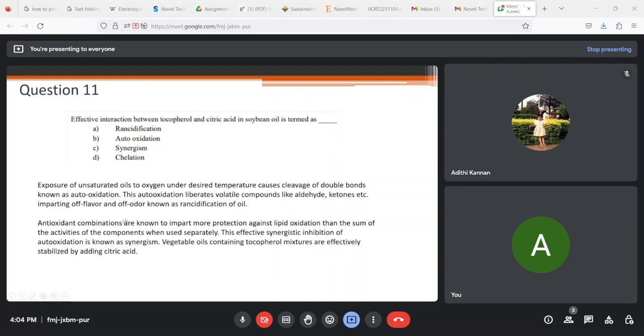Antioxidant combinations are known to impart more protection against lipid oxidation than the sum of the individual activities of the components when used separately. So instead of using them separately, if you add them in combination, that imparts more protection. This effective synergistic inhibition of auto-oxidation is known as synergism. And so vegetable oils containing tocopherol mixtures are effectively stabilized by adding citric acid. Basically, if you add tocopherol and citric acid, that has a better ability to prevent lipid oxidation when compared to just tocopherol or just citric acid. So this is an example of synergism.